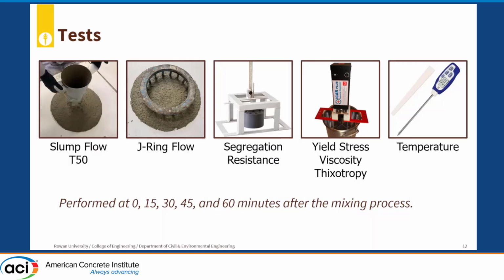This is the rapid cylinder penetration test. As you can see, there's a gray cylinder there. Before you pull the cone from the slump flow test, you mount this apparatus here. Let the concrete stabilize for 80 seconds and then twist the knob to drop the cylinder for 30 seconds. The amount of penetration will describe the amount of segregation. So if you have more penetration, then you have less segregation resistance.